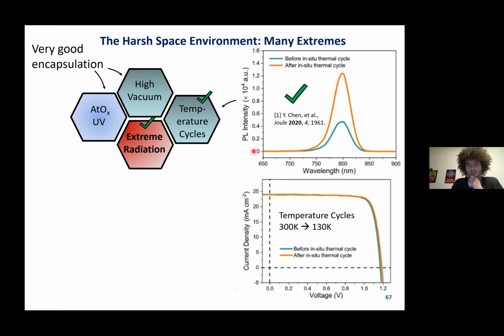Interestingly, there are a couple of studies, for example, by Chen et al. Here, they showed if you have a temperature cycling of perovskite, you can actually improve the PL and improve the JV curve after that. And they speculate that you heal defects in the material upon undergoing these temperature cycles. So this, again, looks promising.